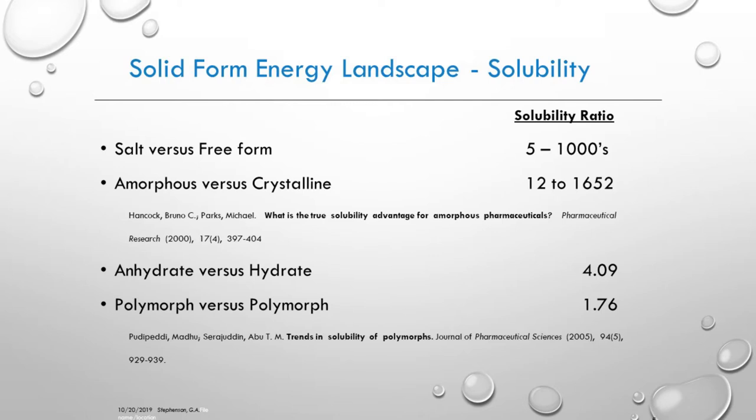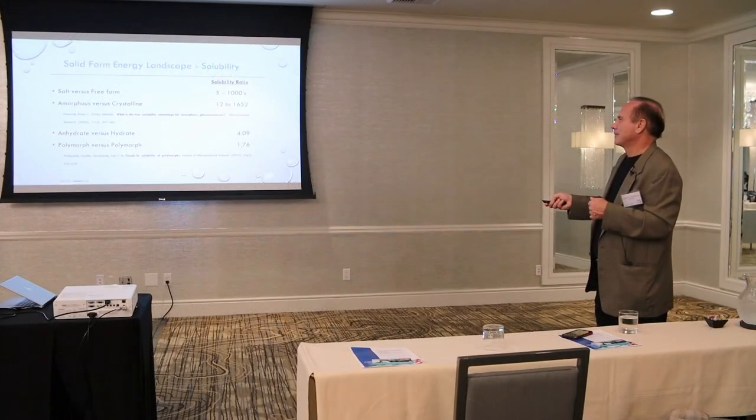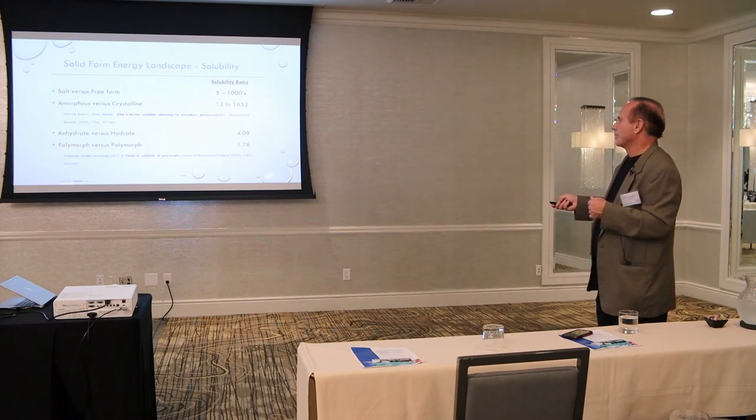These are still significant differences, much less so in solubility ratio, but a hydrated form versus an anhydrate typically — the hydrate is about a quarter the solubility of the anhydrate in water.